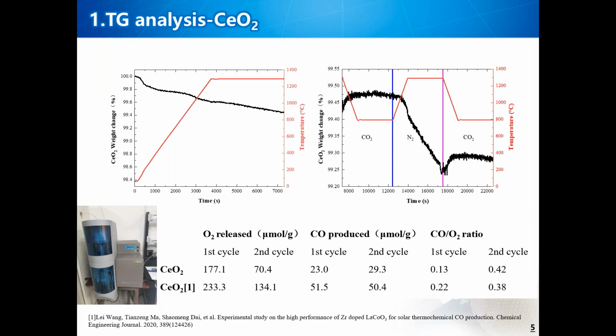We can obtain the oxygen and CO output per gram of material through data analysis. It was found that both the amount of oxygen released and the amount of carbon monoxide produced were lower than the data provided in the paper, but the ratio was close, which indicated that the TG experimental measurement has a certain accuracy.